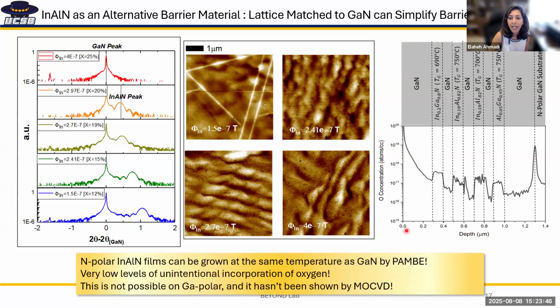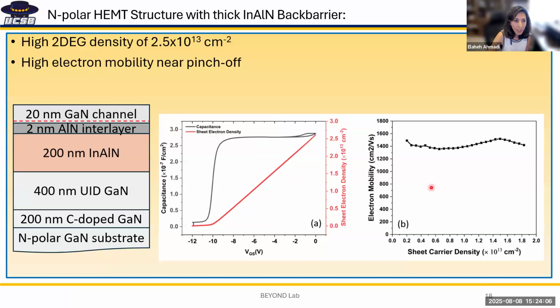to gallium nitride. And by SIMS also, we confirmed that the oxygen impurity, now because we can grow at high temperature, the oxygen incorporation is very low, in low 10 to the 17, which is similar to what we see in aluminum gallium nitride. Now, using this newly developed material in our group, we grew the HEMT structure with 200 nanometer of indium aluminum nitride, because we can do it, because it's lattice matched.